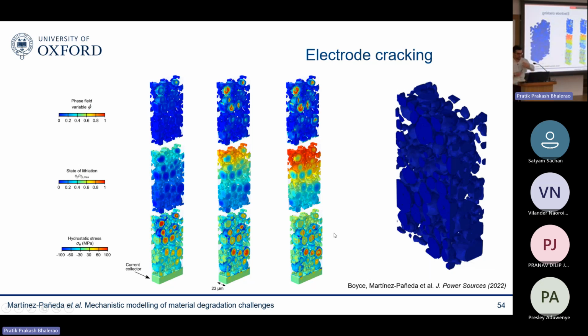So what we see here is the distribution of damage, lithiation, so the concentration of lithium, and hydrostatic stresses. And then we can use our model to, this video is not showing well, but anyway, this is what is expected. The video is just showing particle cracking along your component. So you can use this tool, for example, to answer questions related to the heterogeneity of the electrochemistry.